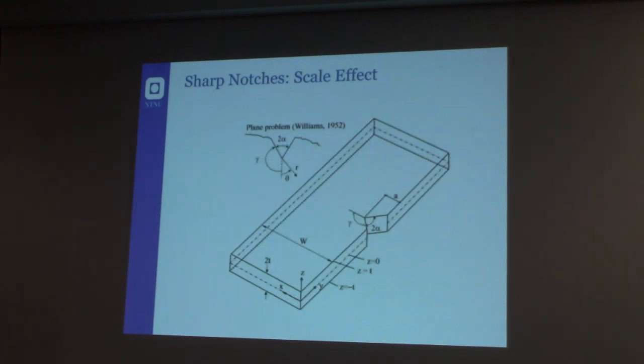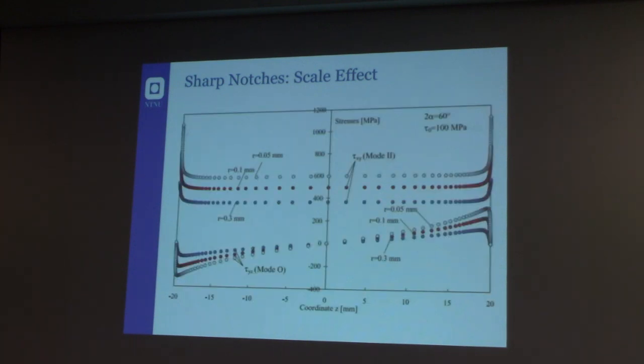What is also very interesting is that, following the rules of linear elastic fracture mechanics, it is possible to use a scale effect because we are in the linear elastic hypothesis. So if you scale this plate in geometrical proportion, increasing or decreasing all the dimensions of the plate, you can also obtain a scaled stress field, following the rules of linear elastic fracture mechanics for the generating mode, that was mode 2, and for the induced mode, that is a kind of out-of-plane mode. We made this kind of study to understand if the scale effect was respected also for three-dimensional coupled modes, and in fact it was.